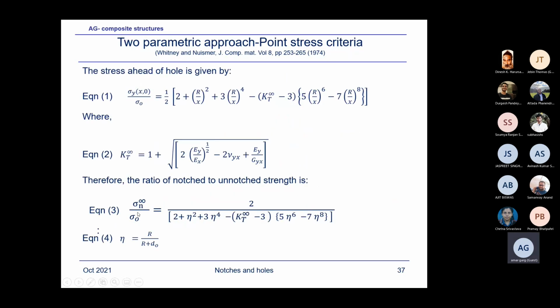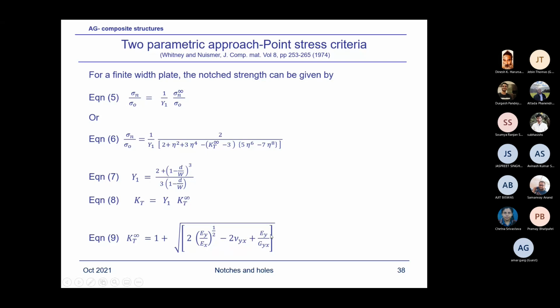So this is for an infinite plate, when the hole is small compared to the plate size. This is the expression for the residual strength, where eta is equal to r upon r plus d naught. D naught is the characteristic dimension, r is the radius of the hole. And for a finite width plate, we apply this correction Y1, which is the correction factor. So sigma n, the notch strength for the finite width plate, is equal to 1 upon Y1, sigma n infinity upon sigma naught. So the final expression is this one, where Y1 is a finite width correction factor, which we have taken, say, from Peterson or any book. Okay. So this is the point stress criteria equation, which is very handy to determine the residual strength for the laminate with the hole.